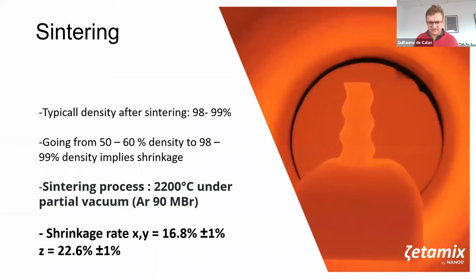So that's the sintering condition, and here you have the shrinkage. You can see there's quite a difference between X, Y, and Z, which happens with some other filaments, it really depends on materials. Here the difference is quite significant. And we reach densities up to more than 98%. 99 would be really high for silicon carbide, but 98% is what we can achieve with this material.